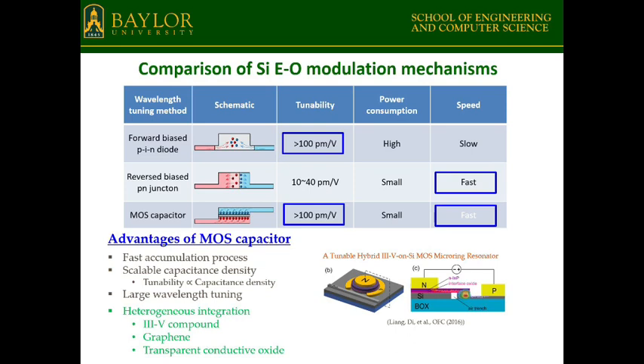And most important, you don't really need to limit your material choice to silicon. For example, you have this silicon waveguide, but the gate material doesn't need to be silicon. You can have different types of material integrated on top of silicon. For example, we can integrate III-V compound semiconductor, graphene, or the transparent conductive oxide. So using this heterogeneously integrated material system, you can greatly enhance the electro-optical modulation efficiency.